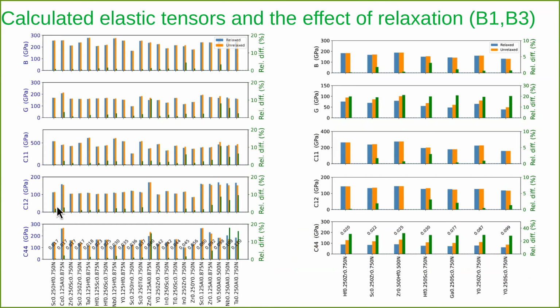All these constants are the average elastic constants for the B1 structures and also the B3 structures. What you see here, as I emphasized on the previous slide, is that the B3 structures are much more severe in terms of computational cost. You need to run longer, and then you need to relax them more properly. It is reflected also here in the difference between the relaxed and unrelaxed calculated elastic constants, because that's what we also do at the end. It can actually be more significant.